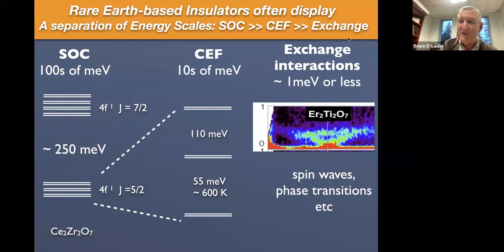And then finally you get down to what condensed matter physicists are mostly interested in, and that is the inter rare earth ion exchange interactions, which are relatively weak because the rare earth 4f wave functions are relatively localized. And so these tend to be on an energy scale of about 1 meV. And it's these very low energy scale interactions that interest most physicists, because this is what's really responsible for phase transitions, if there are any, and elementary excitations and such.